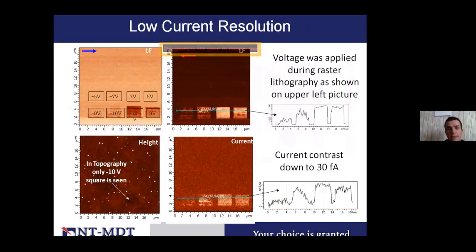Here you can see an example of voltage lithography, and again there is a semiconductor film, and you can see that on the topography image, on the bottom left, there is nothing visible. But if you apply different measuring modes, one is the current, for example, on the bottom right, you can see some current contrast, which shows us some differences down to only 30 femtoamperes resolution. So it's a very high resolution for the current.